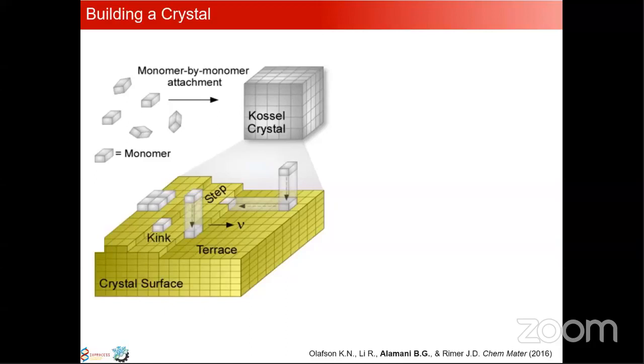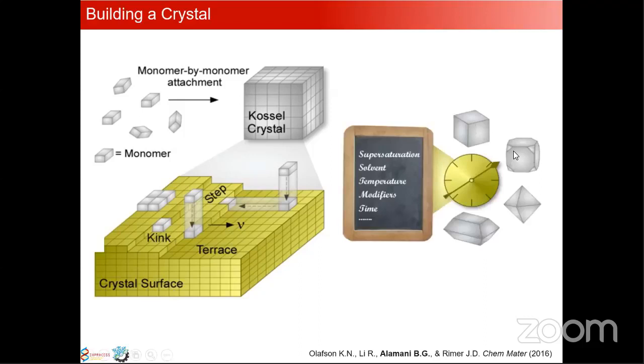Now, macroscopically, or at least in experiments, how do we control this? We do this by changing many parameters, such as supersaturation, which is the driving force of crystallization, choosing a different solvent, or switching temperature. In the case of the experiment we are presenting, we change the modifier, choosing a certain modifier. You can also tweak it using time, which is very common in hydrothermal synthesis for zeolites and metal oxides, where you use time as one of your key variables to optimize the crystallization process.